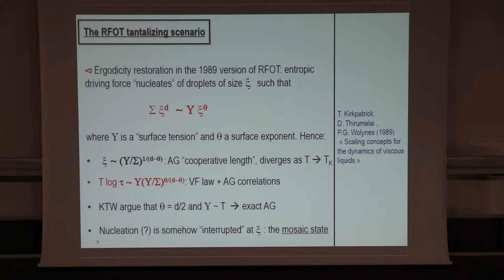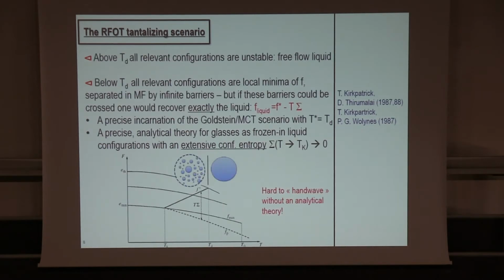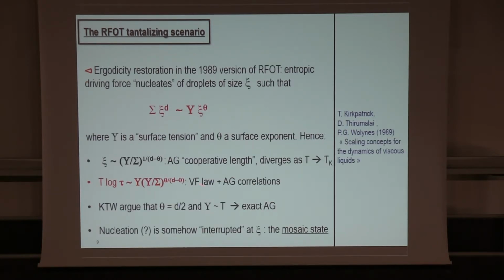this configurational entropy that is somehow counterbalanced by a surface energy between different states that scales with the size of the bubbles to some exponent theta, and Y or epsilon here is some kind of surface tension. And if you assume that something like this is the case, then what's interesting from a phenomenological point of view is that you can derive immediately a length scale that is inversely proportional to the configurational entropy to some power. And you remember that this configurational entropy actually goes to 0 at Tk, like in the REM. And so there's indeed a kind of Adam-Gibbs cooperative length that diverges as T goes to Tk.